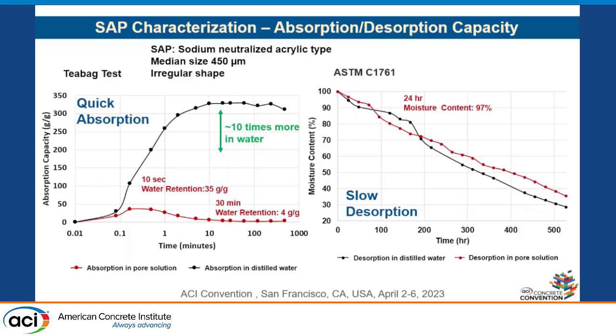And as you see there, there's another important issue. It's about the time. If we assume that printing open time is about 30 minutes, if you look at those times, you will see that at 10 seconds right after addition of water to SAP or pore solution to SAP, let's say the water that is retained is about 35 grams of water per every gram of SAP. So it means that your mixture will dry out immediately after 10 seconds. And after 30 minutes, which is about our open time, that water retention goes all the way down to 4 grams per gram of SAP.